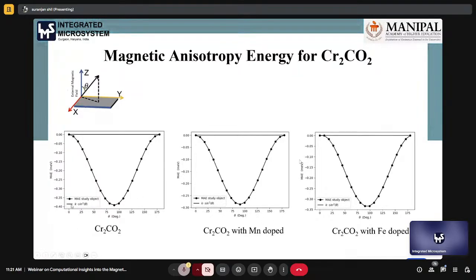We see that chromium carbide without doping has around minus 0.38 or something, but here it goes in the positive direction. Here also it goes in the positive direction. That means when you dope this chromium carbide with another metal, the electronic structure changes, and we can see that the magnetic anisotropy value increases in the positive direction. So that means we can change the magnetic anisotropy value a little bit with the doping with manganese and iron.